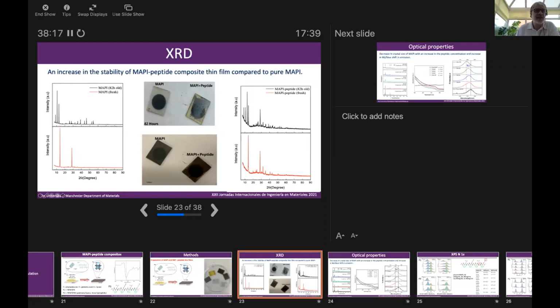So the MAPI peak would be this one and this one here. Most of the methylammonium lead iodide is degraded, as you can see from the picture. With the peptide, we found that there's an almost gel-like structure in the middle, and the stuff around the outside has disappeared. What we think has happened is that the MAPI doesn't actually all go into the peptide. We have some going into the peptide and then some just sitting on top of or around the peptide. And so the stuff which is not encapsulated has degraded, but the stuff which is encapsulated has been protected from the moisture for at least 82 hours.